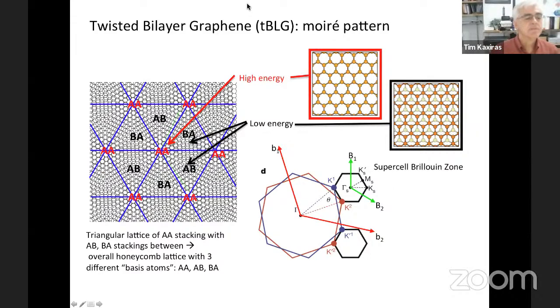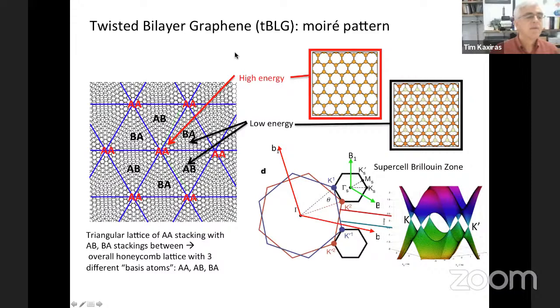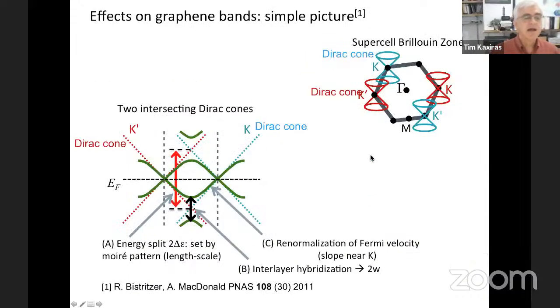Now, this is where the Dirac cones appear in terms of the single layers, and of course these single layers now are combined, and there's a Dirac cone at each corner from the different layers. So there's a Dirac cone from the blue layer here, and the Dirac cone from the red layer here. This is the black supercell Brillouin zone, the small hexagon. And of course, these Dirac cones intersect, and here are the two Dirac cones, blue and red, that intersect.